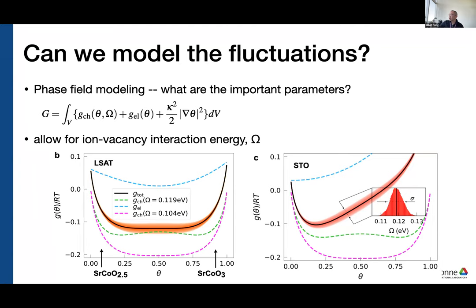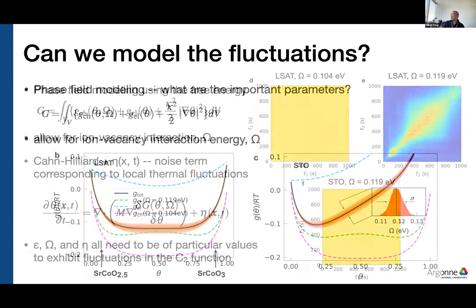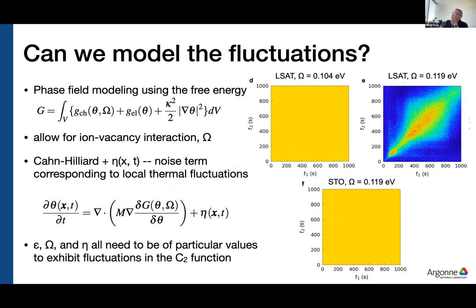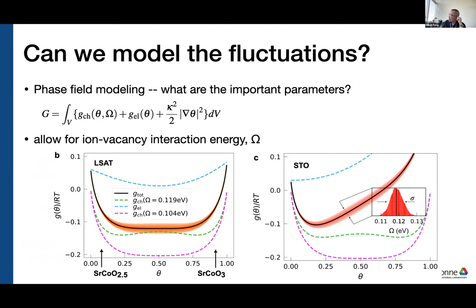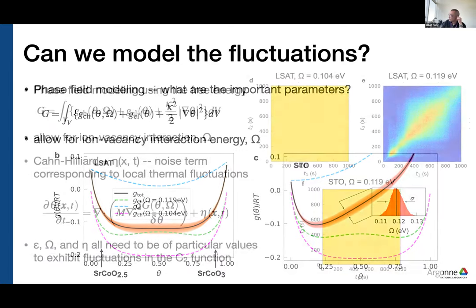So if we go with that 0.119 eV, the SCO on LSAT is flat. The one on STO is not flat. It's favoring the 2.5 oxygen concentration. So that's a simple energy model. It doesn't say anything about these two-time correlation maps that we see.